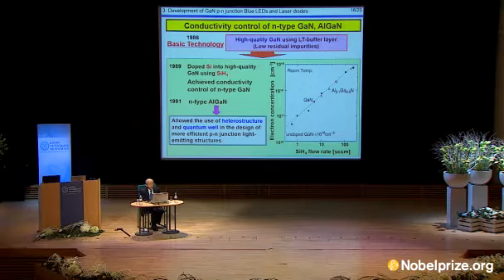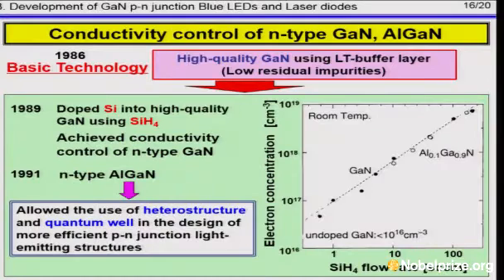Now, I'd like to show you conductivity control of N-type nitride. In the meantime, we noticed that the use of low temperature buffer layer resulted in a marked decrease in the residual donor concentration, causing the N-type crystal to have a high resistivity. In the real setting of device fabrication, conductivity control over a wide range is needed.